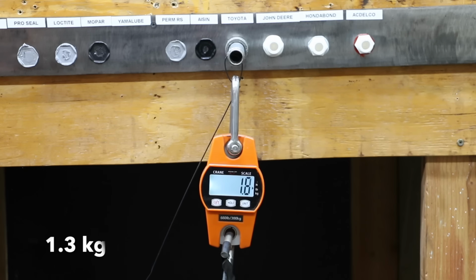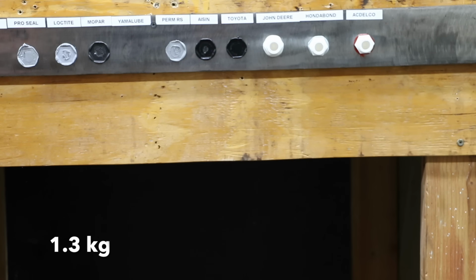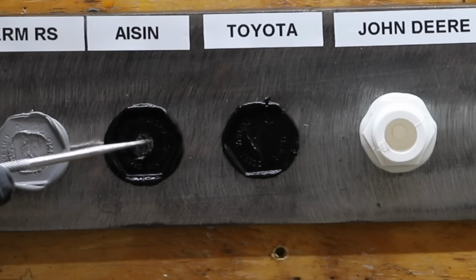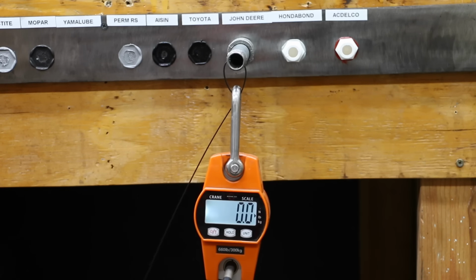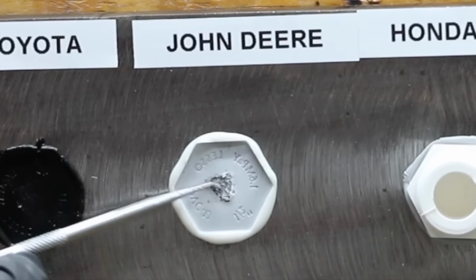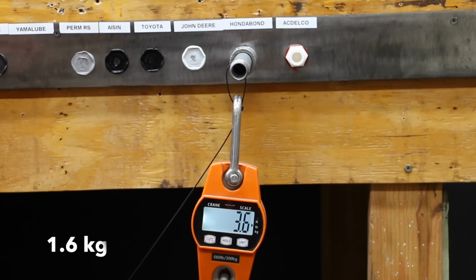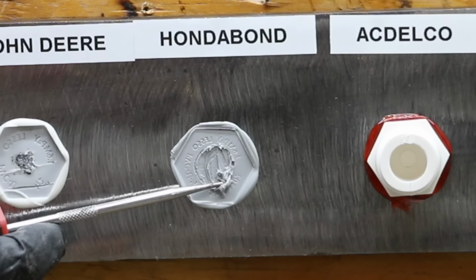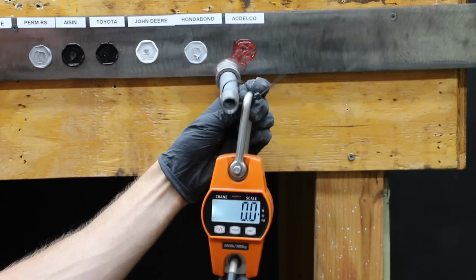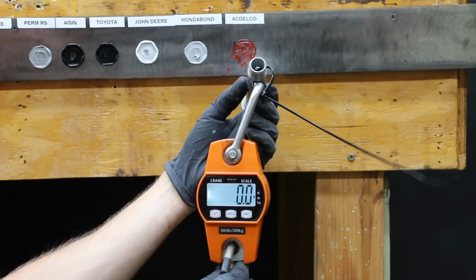And the Toyota is a little bit stronger than the AISIN at 2.8 pounds. Unlike the AISIN, the Toyota is fully cured. Unfortunately, the John Deere didn't even make it off of zero before letting go. And the Hondabond performed better than average at 3.6 pounds before letting go. Unfortunately, the AC Delco did not cure, and it let go while it was still on zero.